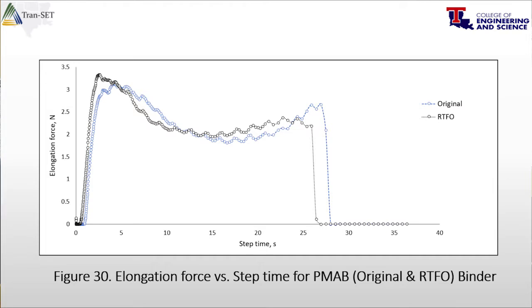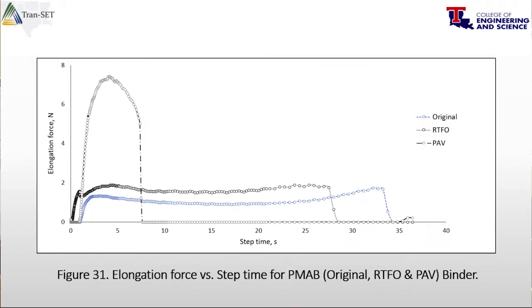Okay, now the polymer modified binder, when you age it, as I said, we didn't have the results for the PAV at 0 degrees when we presented and submitted this paper. It was a problem. So now we have the results, and you can see this is the original binder, and this is the RTFO aged binder. You can see the first peak, the aged asphalt, went up, but the second peak went down a little bit. So we interpret from this that this is due to the aging.